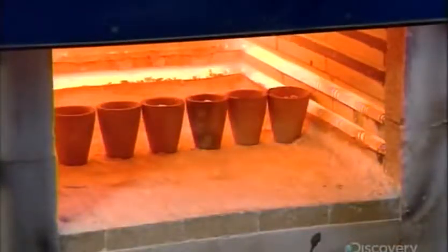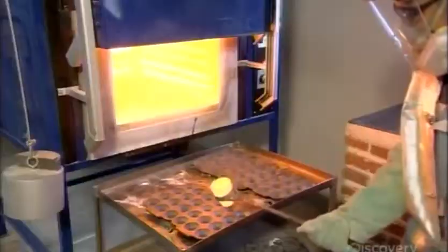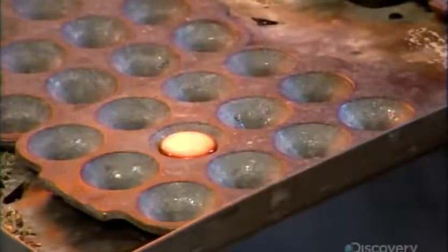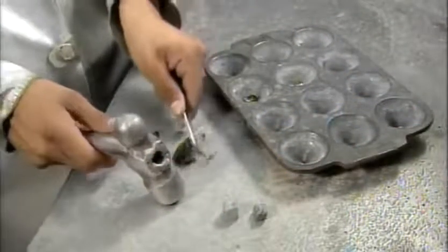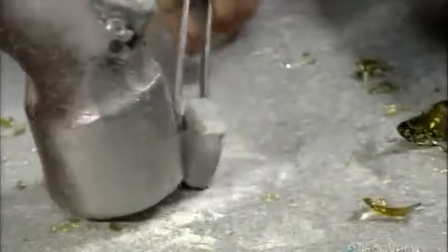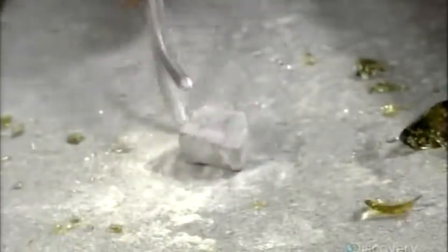a couple of hours. In the mining company's lab, technicians continuously test ore samples to determine the grade, the term for the quantity of silver per kilogram of ore. They heat the samples to 1093 degrees Celsius for about an hour to burn off the impurities. What's left after the burn-off are the silver and other metals, such as lead, zinc, copper, selenium, and cadmium.